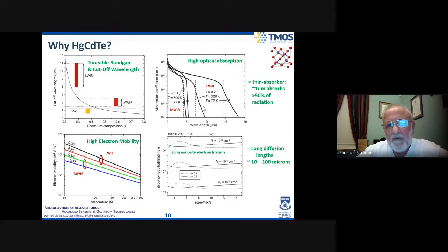If I look at the absorption coefficient, notice below cutoff, I have an absorption coefficient of around 10 to the 4. That means, in inverse centimeters, that I only need about a micron of material to absorb 50% of the radiation.